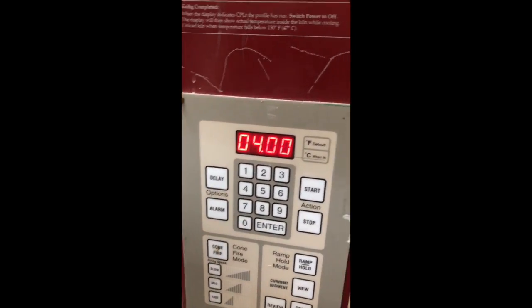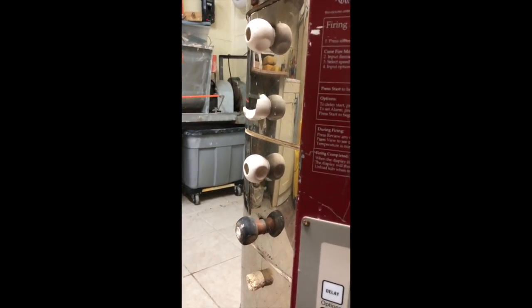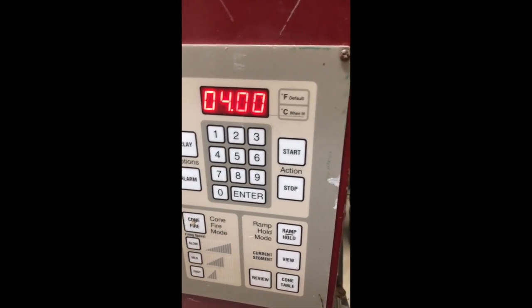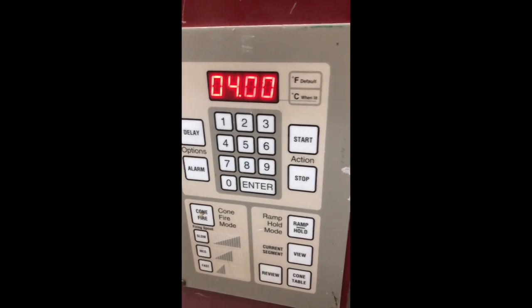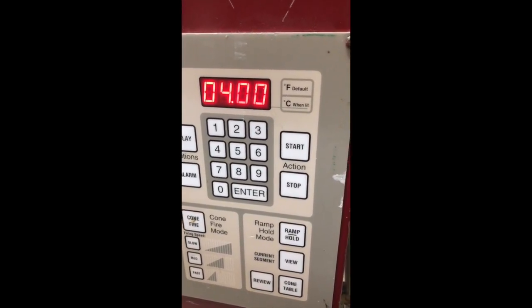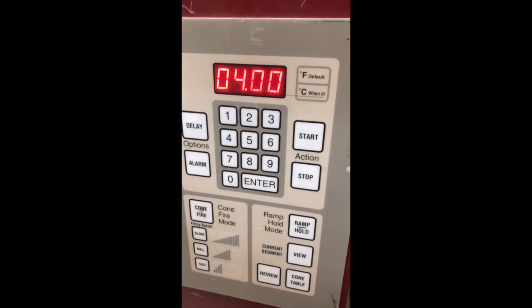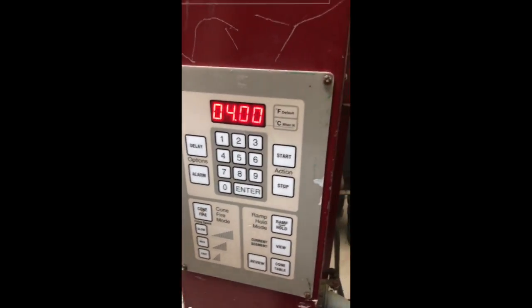After four hours I will check the kiln — I'll pull out a spy and look for steam. If there's steam, I'll run the program again for another four hours. If two hours works better and you want to check every two hours, that's fine too. But running it for a fixed amount whether two or eight hours means you could waste electricity, or fire too short and blow stuff up.